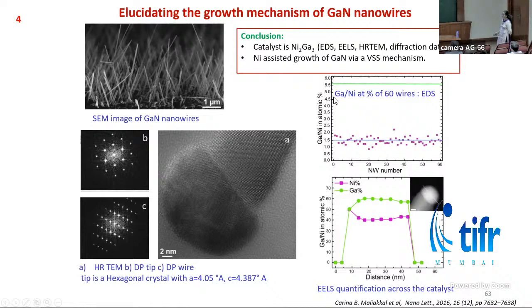So we did EDX on the tips of 60 such nanowires, and we found that the tip composition was Ni2Ga3. When we did an EELS line scan across the catalytic tip, we found that this tip was single crystalline, and again the EELS data also confirmed that it is Ni2Ga3. When we did high resolution imaging of the tip, we could see that it has a hexagonal crystal structure with these lattice parameters. This also matched with a Ni2Ga3 tip. It confirmed that the tip is Ni2Ga3.